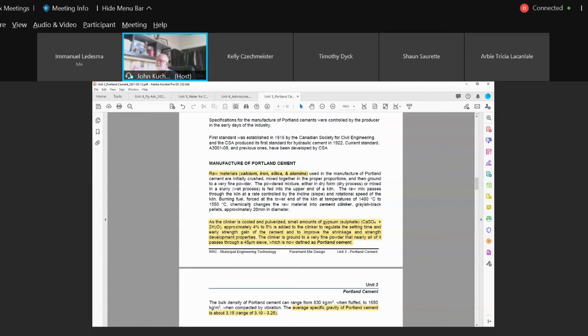The raw mix passes through the kiln at a rate controlled by the incline, the slope, because the aggregates go from one end of the kiln to the other as it's being heated. If you want it to go through quicker, you give it more of an incline and the aggregate falls quicker; if you want it slower, they adjust the incline. The temperature is around 1400 to 1500 degrees C, so you're doing a chemical change of the ingredients.